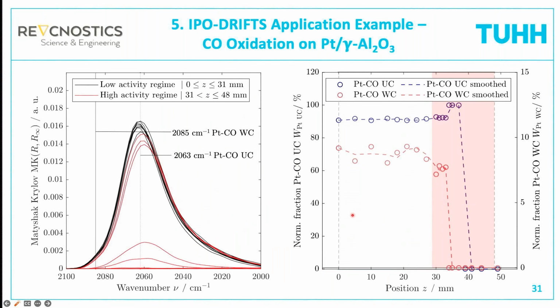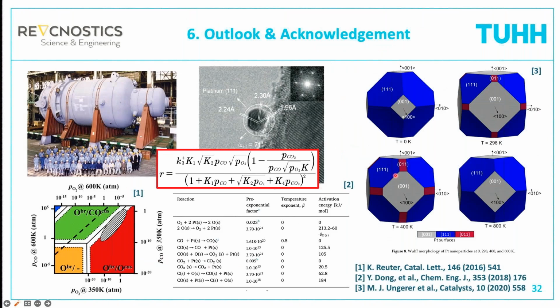You can compare the coverage profile of the CO that sits on well-coordinated sites, here the red curve, with the coverage profile of CO that is under-coordinated. You see the well-coordinated CO is much less strongly bound, so it desorbs earlier than the CO that sits on the under-coordinated sites. What you learn from this is that we have different sites that are differently populated and contribute differently to the reactivity.